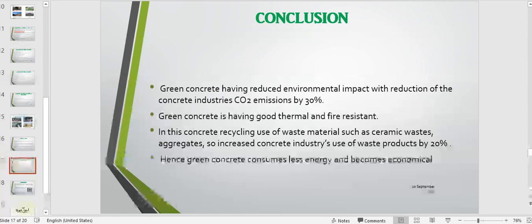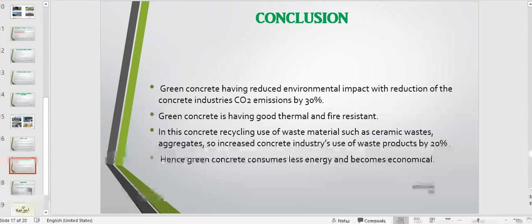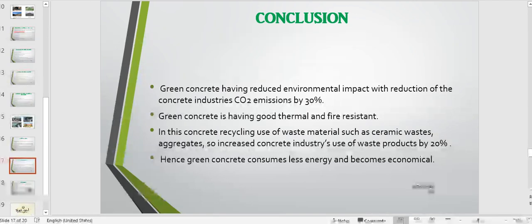Conclusion: although there are some defects of green concrete, everything has both positive and negative impacts. A marginal reduction in compressive and tensile strength of about 10 to 12% compared to conventional concrete has been noticed. For a given water-to-cement ratio, green concrete shows lower workability than conventional concrete due to moisture absorption of recycled aggregate. The problem of global warming and energy crisis cannot be solved in one or two years, but use of green concrete in the future will not only reduce CO2 emissions but will also be economical to produce.